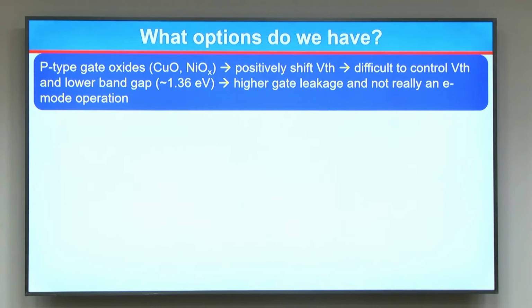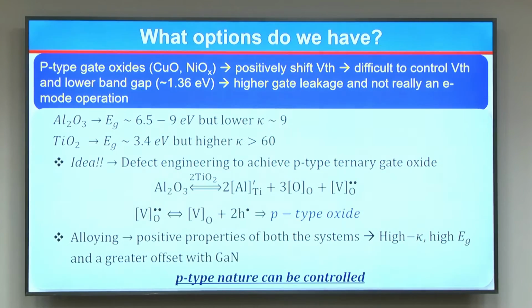There have been several p-type oxides discussed in the literature, like copper oxide, nickel oxide. They have been shown to offer a positive shift in the threshold voltage, but the control on the threshold voltage is often very difficult, and since they have lower band gap, they basically lead to high gate leakage, and also it is not, in real terms, an E mode operation. You see a positive shift in the threshold voltage, but not a positive threshold voltage yet, right.